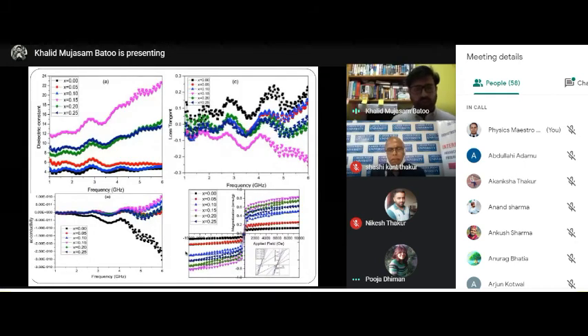Here we tried to study the dielectric properties of these materials, and the dielectric constant showed almost 24, touching 24. The dielectric constant was increasing, and it was highest for 15%. Dielectric loss was very, very low, less than 1, which means the material can survive. It's a very good material for low loss, and the AC conductivity of the material showed it is good also.